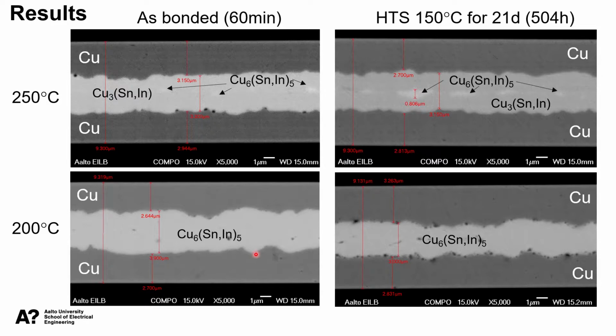The interesting phenomena was found out when we did some solid-state annealing, and we observed that these microstructures seem to be extremely stable against thermal treatments. Here we see the microstructures after 500 hours exposure at 150 degrees centigrade, and we cannot observe any microstructural changes. In fact, these similar results we have obtained also after 1000 hours.